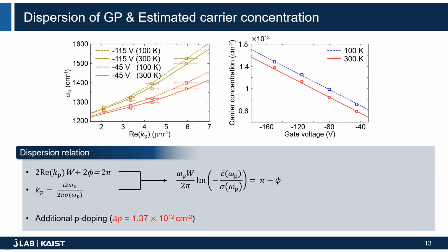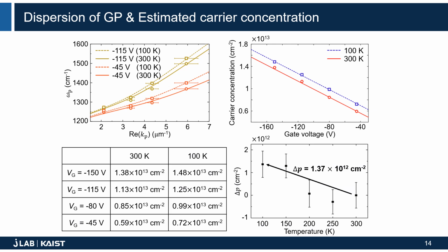To independently estimate the doping level variation associated with cooling, we fit the measured peak position to the theoretical dispersion relation. You can see that the resonance frequency measured at gate bias of minus 115 volts and minus 45 volts, at both 300 and 100 Kelvin, agrees well with the resulting dispersion curve. I summarized the resulting carrier concentration in the table and figure below. The estimated doping levels well match the linear fit with a 300 nanometer oxide capacitance model.